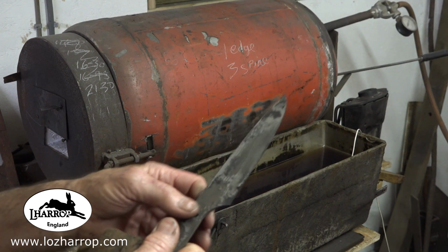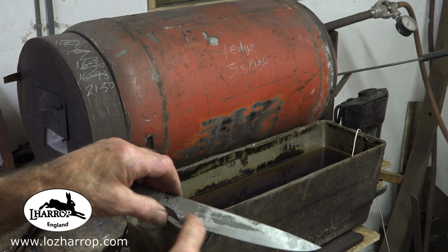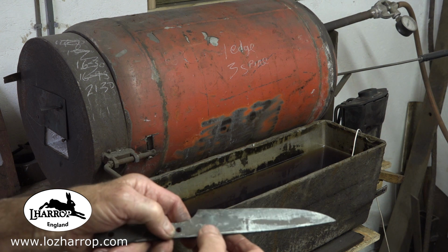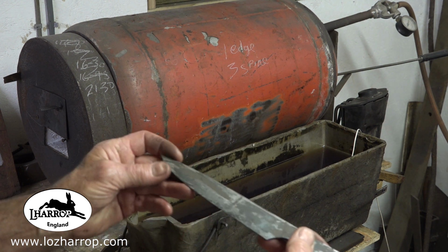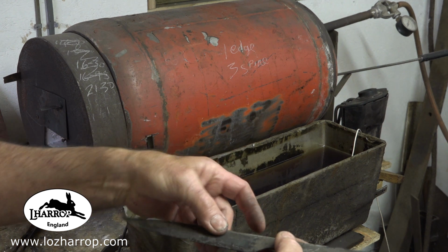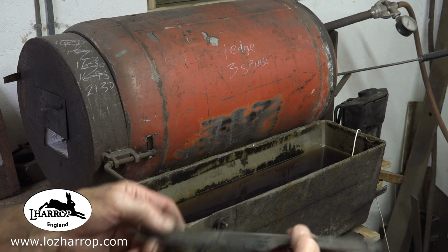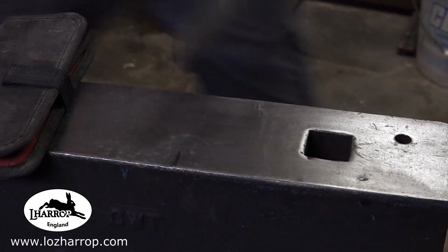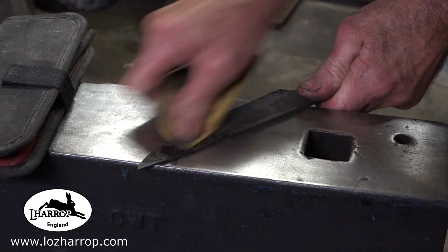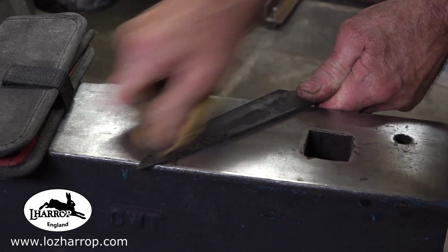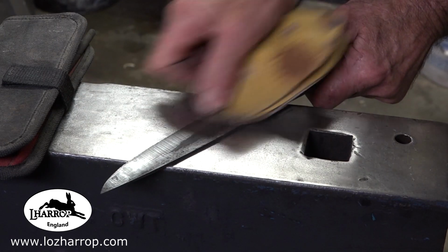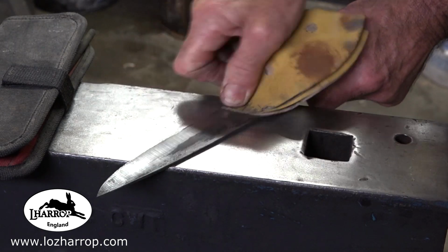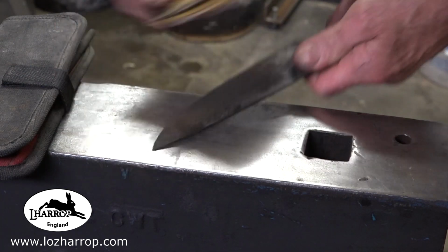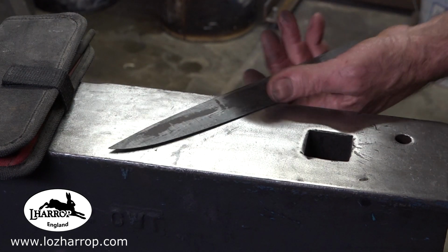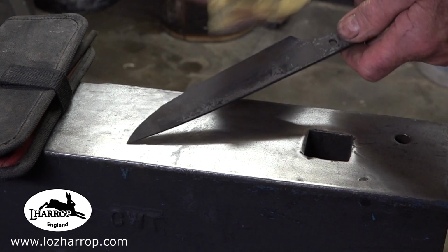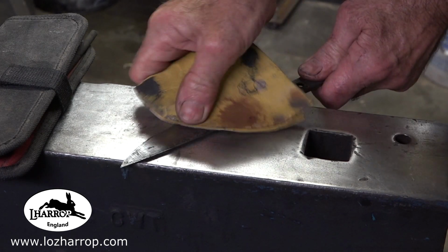Right, I'll just go and get my Rockwell files. I can't test this on my Rockwell machine because I've ground the bevels in, and you can't put a diamond tester on a sloping face, because you won't get an accurate reading usually, but you also run the risk of actually breaking the diamond in the machine. So there will be a bit of decarb on the surface of this steel, a bit of decarburization. The anti-scale does protect that to a degree actually. It stops oxygen hitting the surface and burning up the carbon. I'll just remove that, then I can get a more accurate reading.